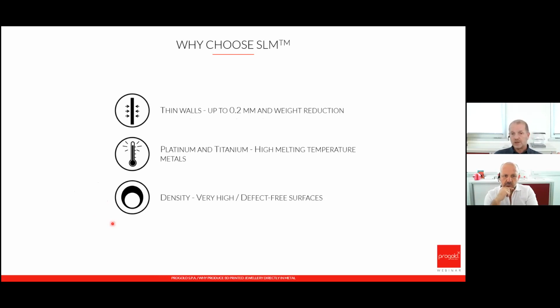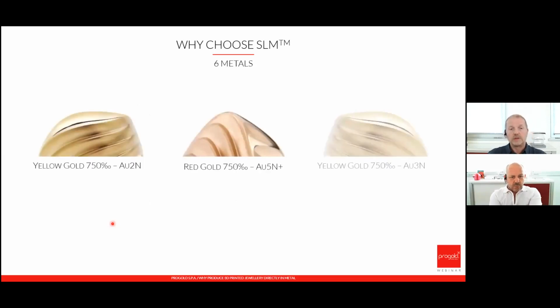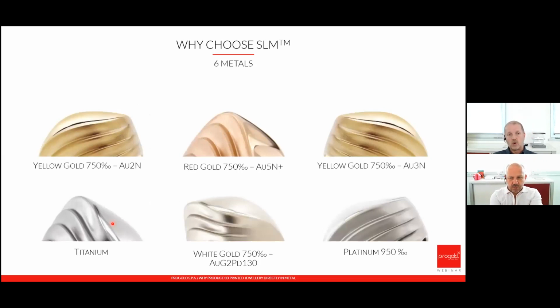It allows very thin walls, up to 0.2 millimeters, reducing so the weight of the parts. SLM is particularly suitable to produce platinum and titanium, high melting temperature metals, and it obtains very impressive density for the parts. With the result of defects-free surfaces. Our bureau operates with 6 metals so far. So we have got 18-karat gold, 2 color of yellow gold, rose gold, and palladium white gold, together with titanium and platinum.